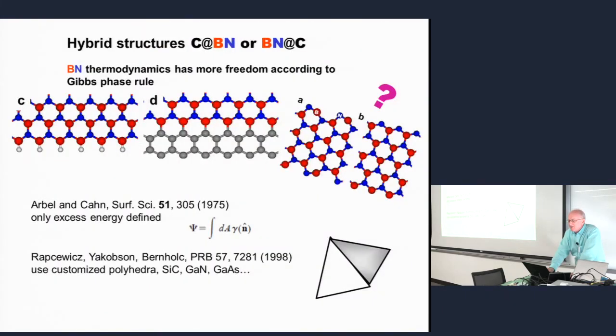Yeah, another maybe important and transferable idea was the analysis of edges or maybe interfaces when you have low symmetry. It's very common for theorists calculating surfaces, and the same way edge energies, by just considering a slab. So normally if you have graphene and you want to find edge energy, you just have a ribbon. You calculate total energy, subtract energy of the perfect lattice, divide by 2, and you have edge energy. The problem is, if you go to boron nitride and all this class, they typically do not have inversion symmetry. Then you have a problem, because if you do the same recipe, you divide by 2, you get a number which doesn't make any physical, at least deep sense.